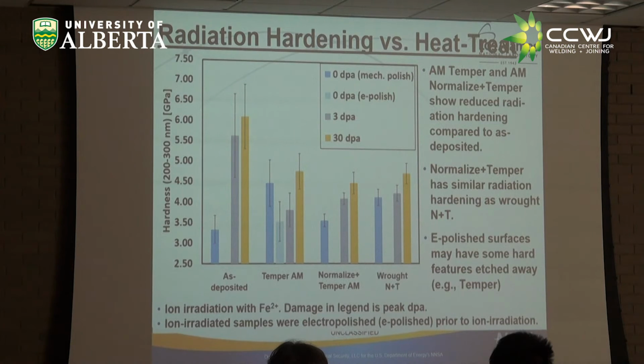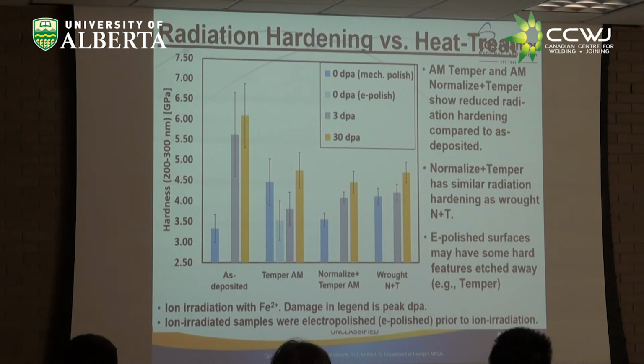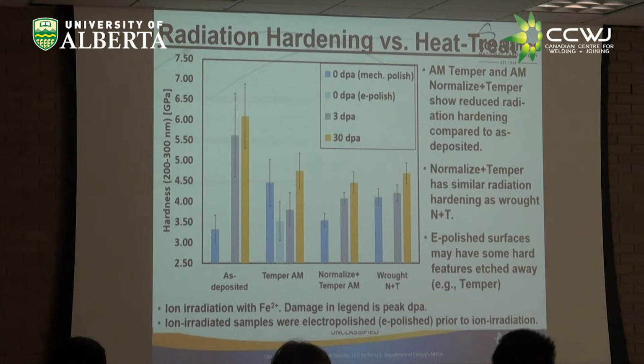The one that was normalized and tempered, and then the wrought, a piece of wrought that we just heat treated, wrought meaning it was cast and then rolled. You see that the normalized and tempered and the wrought have very similar properties, and in fact, if there's anything, the AM normalized and tempered did not see as much irradiation damage hardening as the wrought sample. So it actually ended up, if anything, being better than the wrought material. So there's actually great promise for this, if we can find a way to commercialize this method.